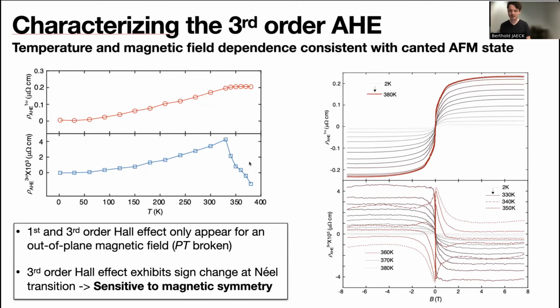Next, what we also did is to study the temperature dependence of this third order anomalous Hall effect. Interestingly, when we started at very low temperature, we observe a rather vanishing signal. As we now increase the temperature from, say, 2 Kelvin to above room temperature, we see essentially a monotonous rise of the anomalous Hall amplitude. And just near the Néel transition temperature, suddenly the signal decreases and changes sign. And this is quite an interesting observation.